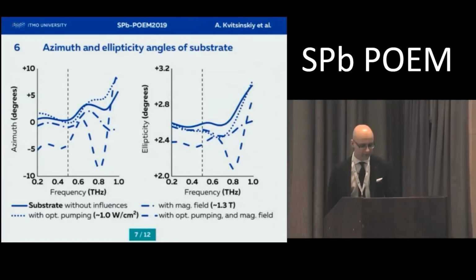On the slide, the frequency dependencies of azimuth and ellipticity angles of the polarization ellipse of the silicon substrate in the frequency range from 0.2 to 1 terahertz. The solid line indicates data without external influences. The dashed line denotes the data obtained with optical pumping of 1 watt per centimeter squared and a magnetic field of 1.3 Tesla. It is seen that the joint use of optical pumping and magnetic field has the greatest influence on the angles. At frequencies from 0.6 terahertz, the amplitude of the value of the azimuth angle is more than 10 degrees.